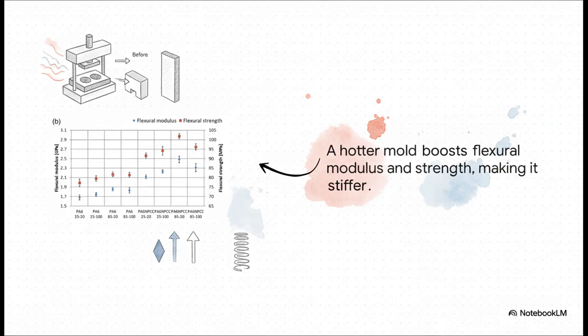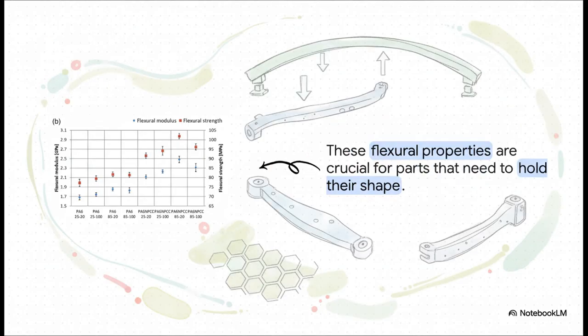On this chart, you can see both the blue diamonds and red squares are way higher for the 85-degree samples. That means it's much harder to bend it out of shape. And that extra stiffness, that's a huge deal. It's absolutely crucial for any structural component that needs to hold its shape when you put it under stress. You know, exactly what you need for an automotive part.